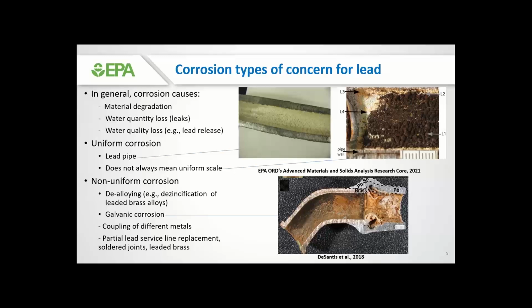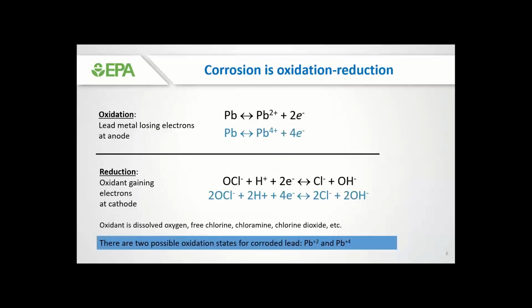This is basically the lead pipe having really been sacrificed, corroded to the extent that we lost a lot of lead from the lead pipe wall into the water, contaminating the water. This is an issue in partial lead service line replacements, in solder joints, in leaded brass, and anytime we have dissimilar metals connected in our drinking water distribution systems. But let's stick with uniform corrosion for simplicity now.